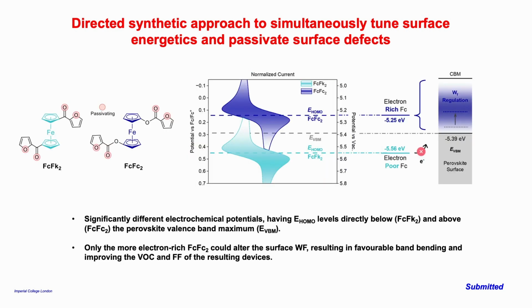And hopefully you can see with this schematic, this is a publication we just submitted last week. Ultimately, we've got, over on the right-hand side, the conduction band and the valence band of our device. So one of the materials has been designed to be lower than the conduction band, and the other material to be higher than the conduction band. So one of the materials is what we call electron-rich, and that actually is then inputting electron density into our perovskite material, whereas the other material is electron-poor, and so that's not able to tune the material and add to our efficiencies.